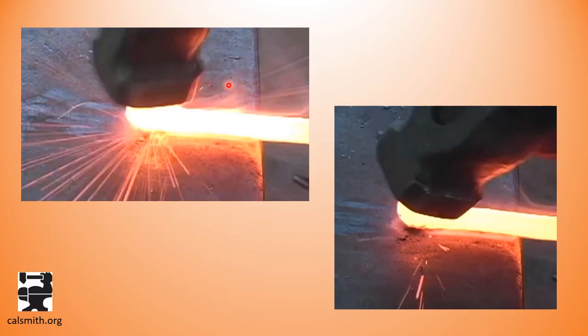Here is a piece heated to welding temperature. You've got your yellow, bright orange. You're going to hit the top with your light to moderate blow, angle your hammer, and with even lighter hits, blend in that toe using good hammer control so that you don't end up thinning the parent bar. Turn that over as long as you have a welding heat, and do the same on the other side.